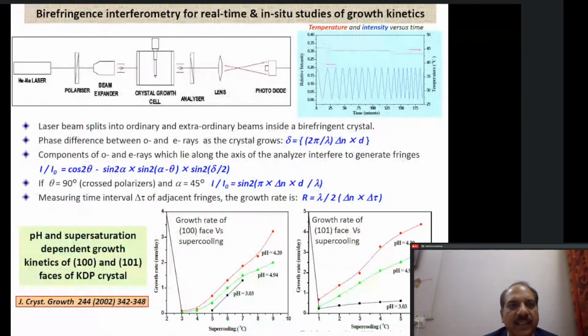Now, there is another technique which we call birefringence interferometry. This technique is used for real-time and in situ studies of growth kinetics. What we do is, if your crystal is birefringent in nature, we can use that birefringent nature to grow a crystal and measure its growth rate in different directions, especially in the direction of birefringence. So the principle is something like this. You have a helium neon laser, you polarize it, and you expand it. Now this polarized laser, when it passes through a crystal which is birefringent along a particular direction, it will split into extraordinary and ordinary ray.